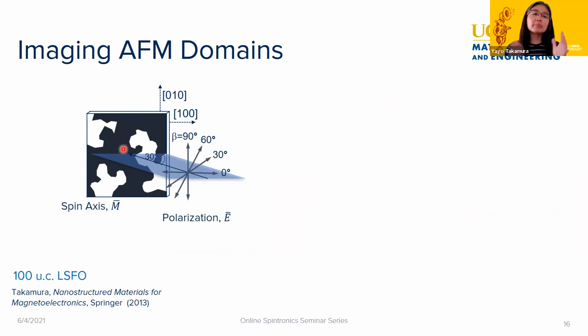But then what we'll actually want to do, if we want to map out in 3 dimensions what is the direction of the antiferromagnetic spin axis, we're actually going to go one step further. And so not just use the vertical polarization of the X-rays. At the PEEM3 microscope, you can actually change the orientation of the E vector. So I'm not just stuck at vertical, I can actually rotate it all the way so that it's horizontal.